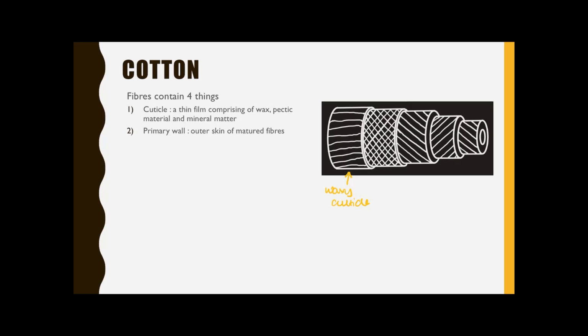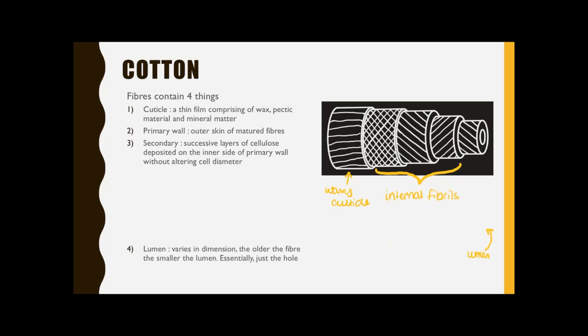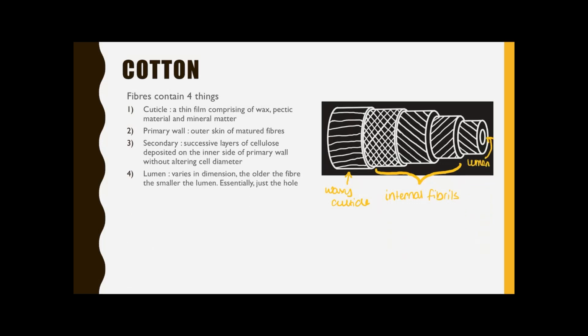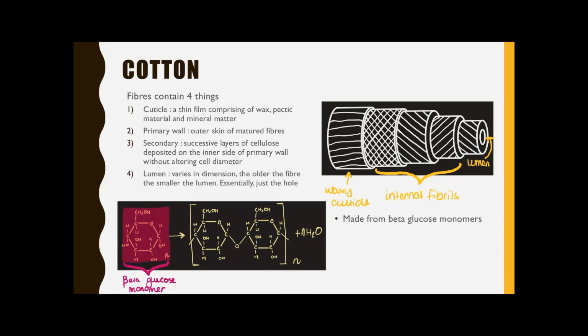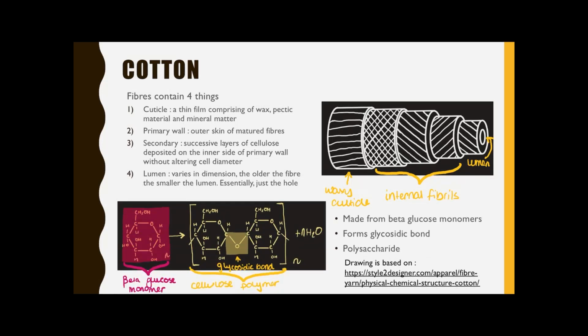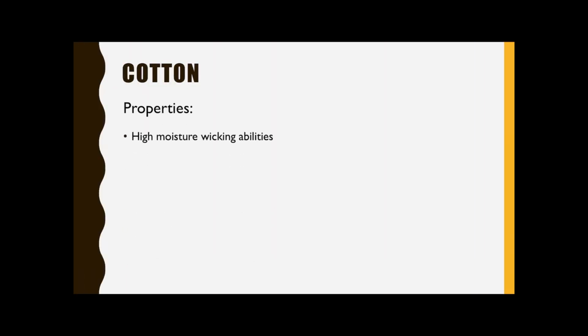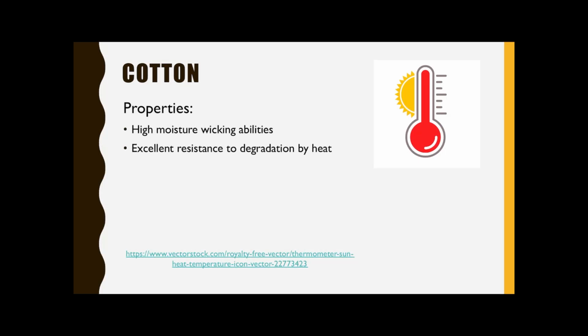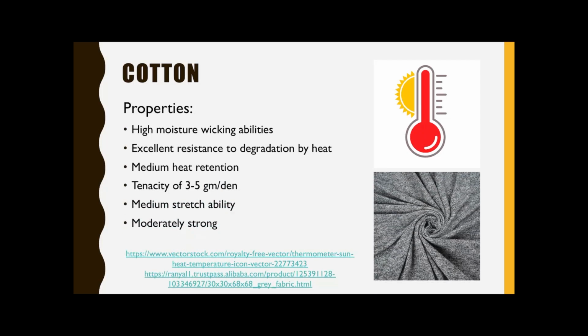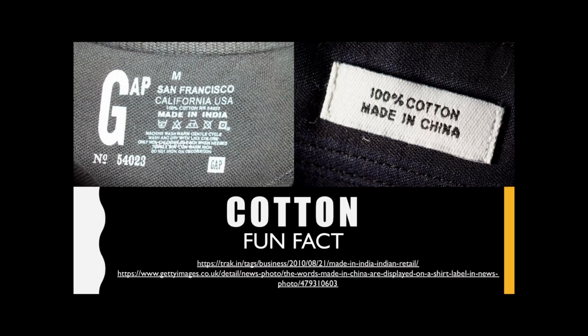Primary wall, which is the outside skin of matured fibers. Secondary wall, which is the successive layers of cellulose. Cellulose is the main polymer in cotton. Lumen, which is actually just the hole. Cellulose is made out of beta-glucose monomers, forms glycosidic bonds, and is a polysaccharide. The properties of cotton include that it has high moisture wicking abilities, excellent resistance to degradation by heat, medium heat retention, tenacity of 3 to 5 grams per denier, and then medium stretchability, and it's moderately strong and breathable.